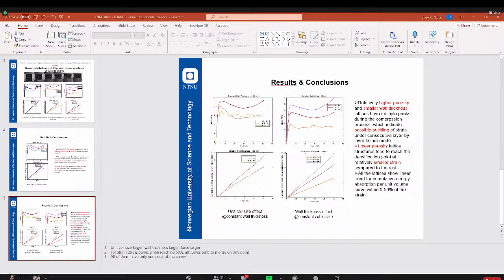So for the unit cell size, we started with the minimum of 4 by 4 by 4, so 4 millimeter by 4 millimeter by 4 millimeter. Based on the cubic size, because for the scale effect we need to have the same porosity, we then increase up to 16 by 16 by 16. So there are 4 different unit cell sizes: 4, 8, 12, and 16.